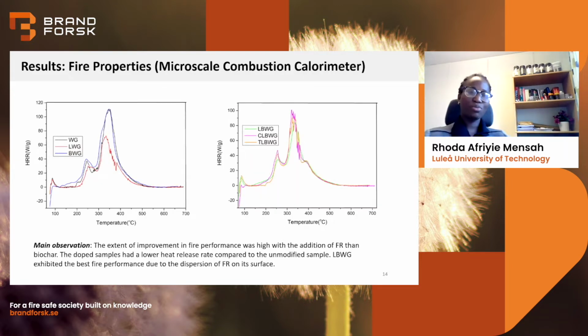For fire properties, we conducted two different experiments. That's the microscale combustion calorimeter experiment, where milligram samples are required, and the cone calorimeter experiment, where we use gram-sized samples. For the microscale combustion calorimeter experiments, we conducted them at 1 Kelvin per second, and the results are plotted as heat release rate versus temperature curve for the undoped samples on the left and the doped samples on the right.